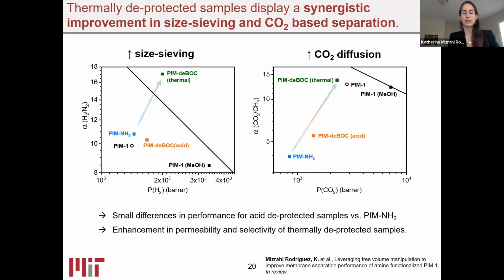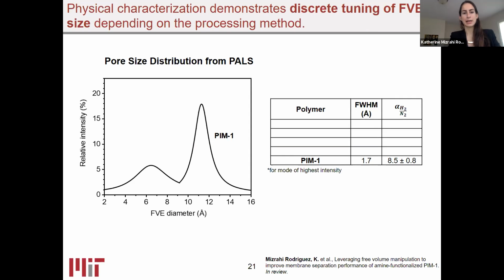Whereas in the thermal case, there's a boost in both permeability and selectivity that was very encouraging and that we think may be associated with the packing structure of the material. So we went ahead to better investigate that packing structure through pore size distribution analysis from positron annihilation lifetime spectroscopy. Here we can see the bimodal distribution for PIM1, and on the right we have a table with the selectivity as well as the full width at half maximum for the modes of highest intensity. When PIM1 is functionalized with the amine, there's a decrease in the free volume element diameter for the large size of the FVE, as well as an increase in the amount of these pores. Essentially, there are more smaller pores in the amine PIM, which results in higher selectivity.